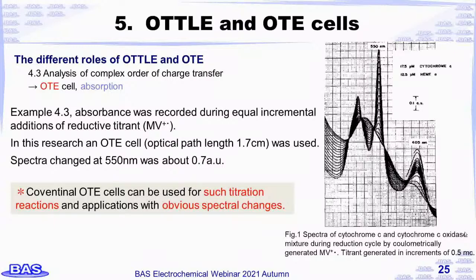Example 4.3. Absorbance of a cytochrome c and cytochrome c oxidase mixture was recorded during equal incremental additions of reductive titrant. In this research, an OTE cell was used. The spectral change at 550 nanometers was about 0.7 AU. Conventional OTE cells can be used for such titration reactions and applications with obvious spectral changes.